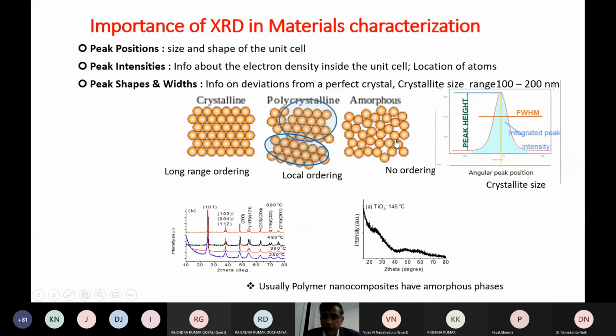We can see that your materials are amorphous. Usually, for amorphous materials we don't see any characteristic HKL lines, as we do for polycrystalline or crystalline materials. The peak position tells us about the unit cell, and the peak intensity gives information about the atom positions, etc. And depending on the width, we can see whether your materials are nano or not.